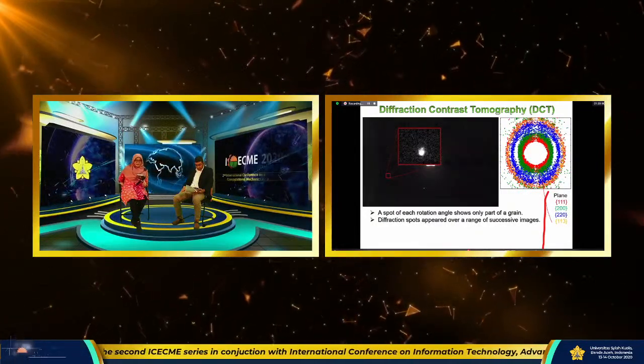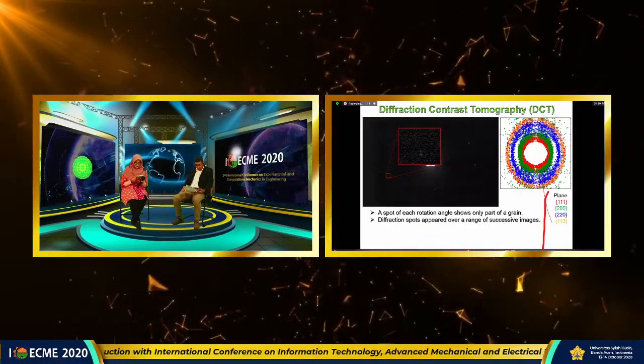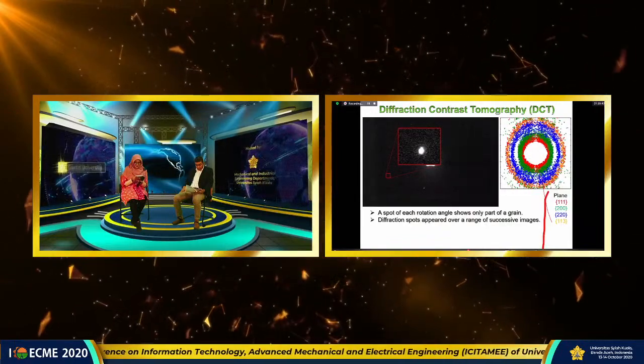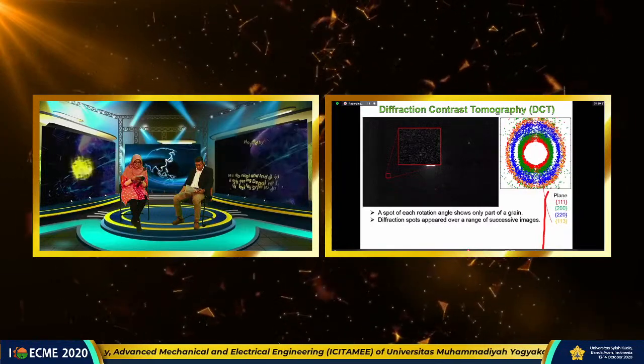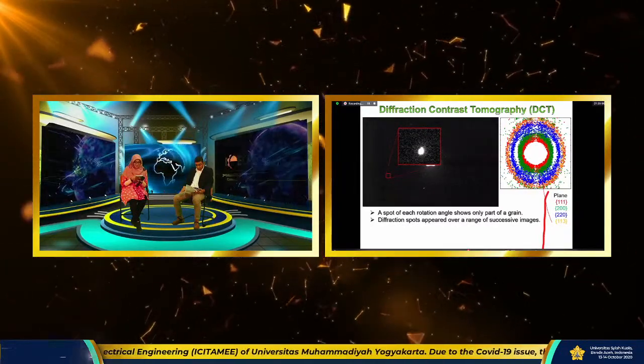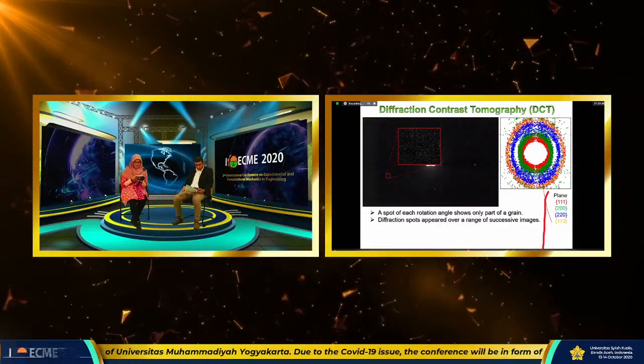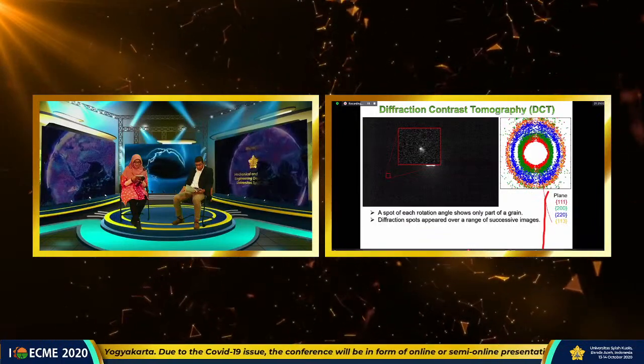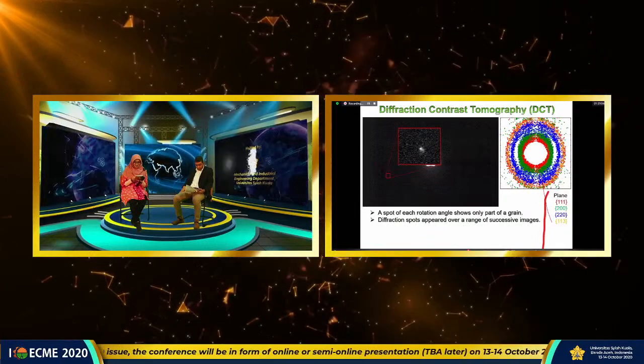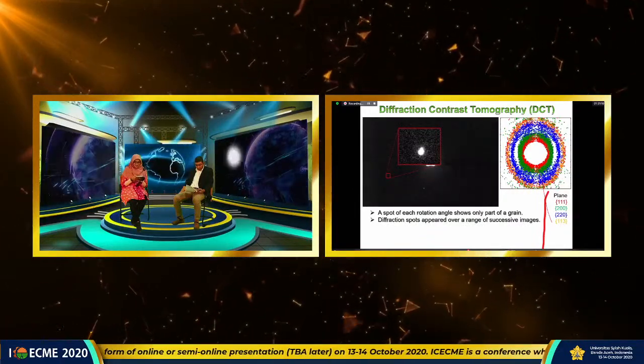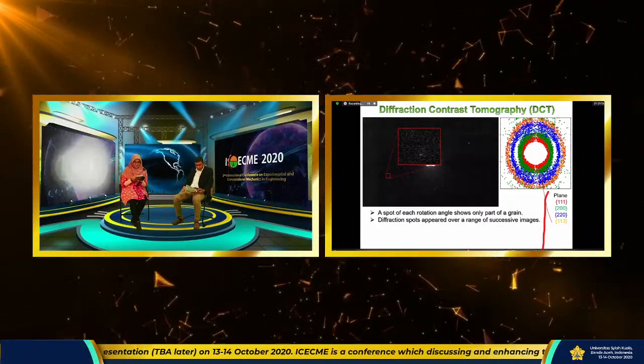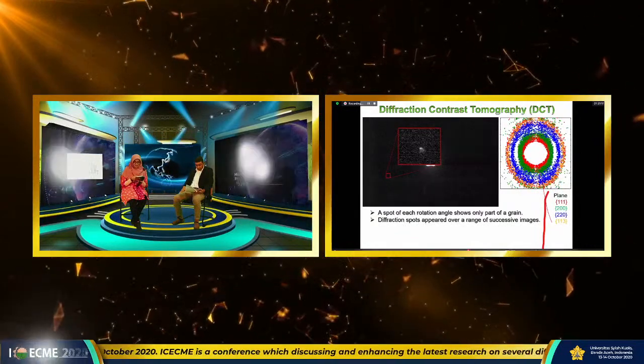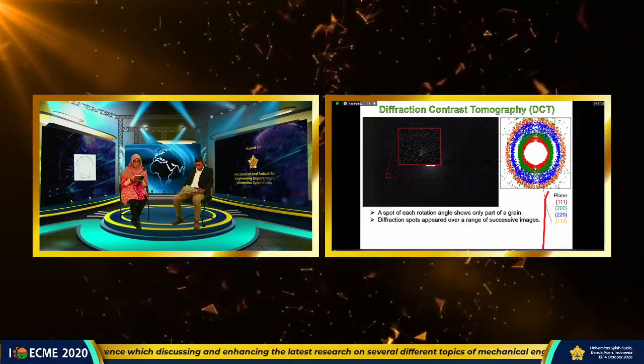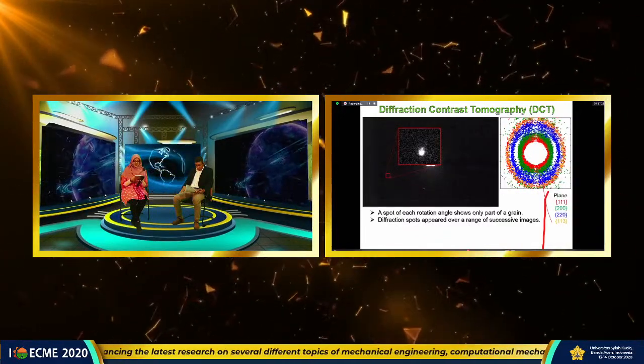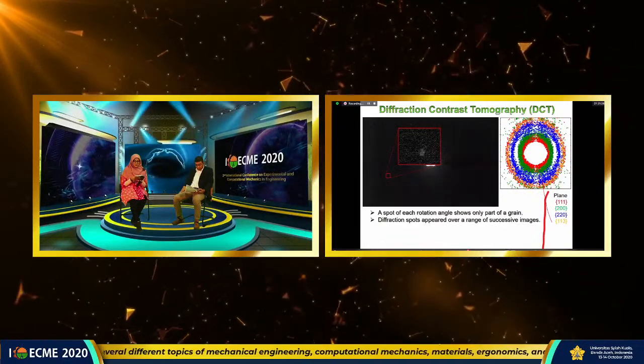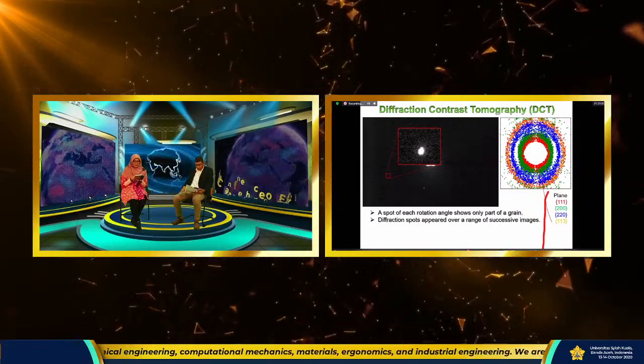Usually, every grain has misorientation due to dislocations. The diffraction and extinction spot images are spread over a range of the rotation angle, and only part of the diffracting grain appears in a projection image at a fixed rotation angle. Therefore, the contributions from the same grain under each diffraction condition should be summed for constructing the image of each grain. This is the original diffraction contrast imaging proposed by the French group. Our developed method uses the rotation angle spread, which gives information on the misorientation of the diffraction plane of individual grains.